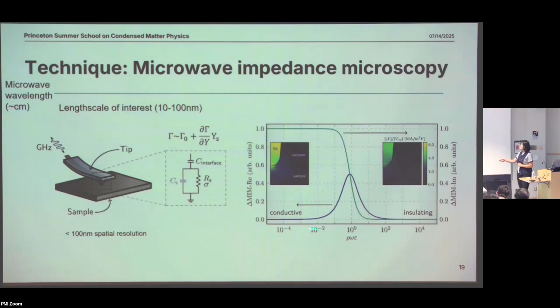So it goes from one extreme to the other, and then the y-axis has the two channels of the microwave coming out. So one channel is the reflected wave, but in phase with the incoming wave, and the other part is out of phase. So as you can tell, if we focus on how it depends on the sample conductivity, then if you look at the right-hand side, the more insulating you get, the smaller this imaginary part you get. And then it monotonically increases when you go to the other side.